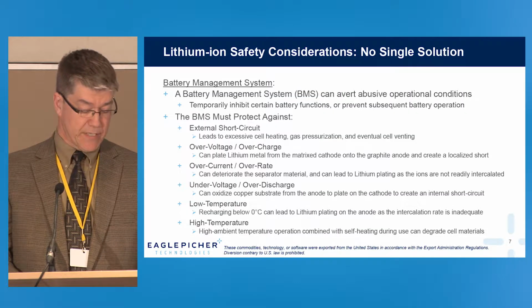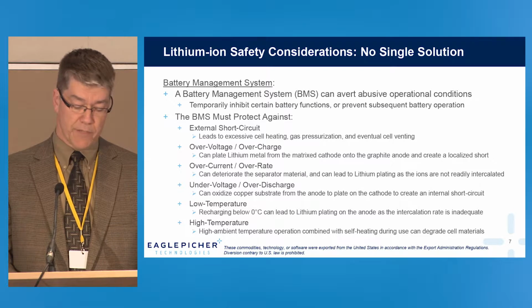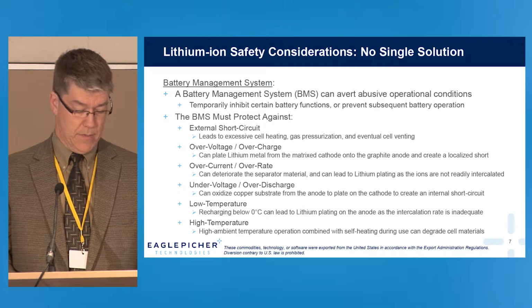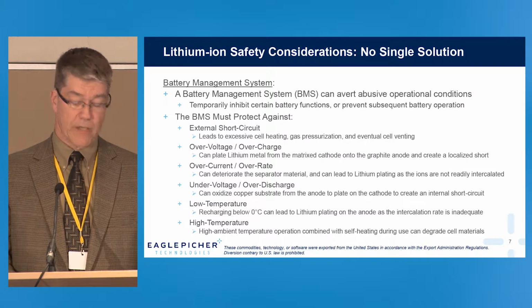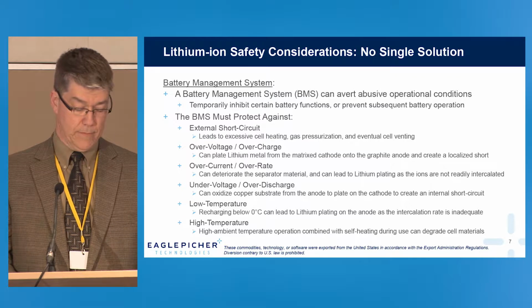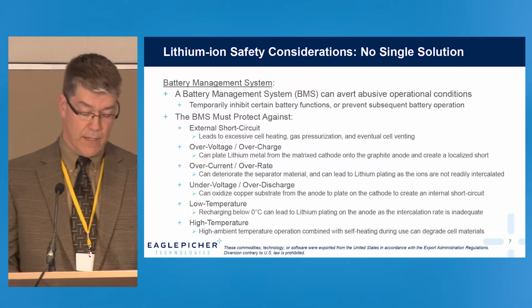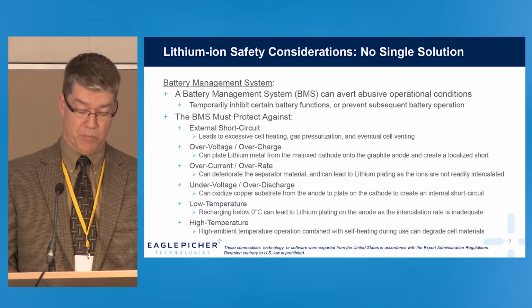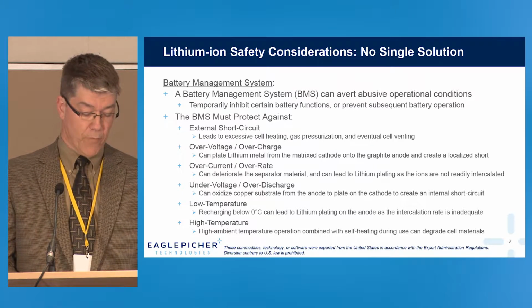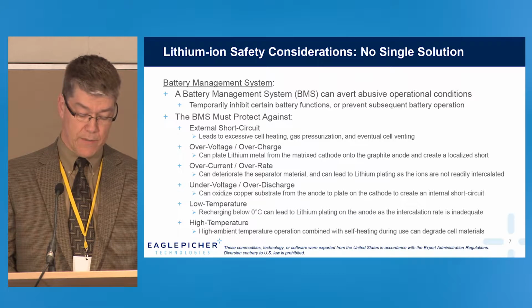So now we'll examine the key elements of a safe battery design. With the battery management system, it's understood that a BMS is required to mitigate against abusive cell conditions, protect against external short circuit that could lead to cell venting, overcharge or overvoltage, which can plate lithium from the matrix cathode onto the anode, overcurrents or overrate, which degrades the separator material and results in plating of lithium, undervoltage or over-discharge, where we actually oxidize copper substrate from the anode to plate on the cathode material.